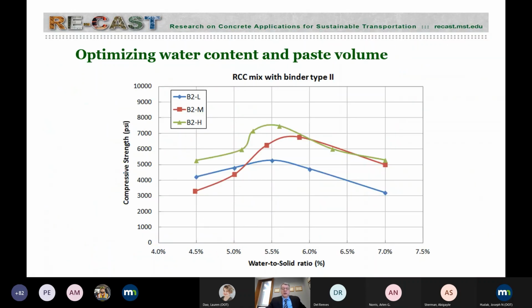We could also look at another set of three figures, again doing the same thing, modified Proctor test. The difference between them is the binder content. The blue one is low, the red one is medium, and the green one is high. So the binder content and the water-to-binder ratio determine the amount of paste. We can see over here that the optimum water content is about 5.5 to 6% consistently, but as you increase the binder content, you get higher density, but also higher compressive and flexural strengths.